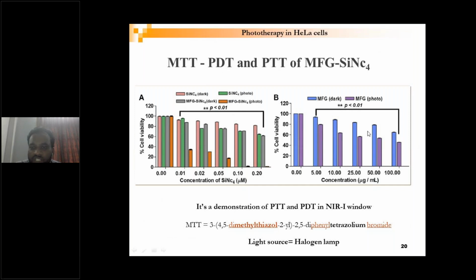Whereas you would like to see what the contribution of MFG is from photothermal therapy. Here we only added MFG without the photosensitizer. The blue one is for dark and the purple one corresponds to light, meaning under light irradiation what efficacy of cell killing we observed. When compared with the dark we got better results, but not that effective from photothermal therapy alone. So we can conclude from this slide that the synergistic therapy has given very good results. And this experiment is done using the NIR1 laser.